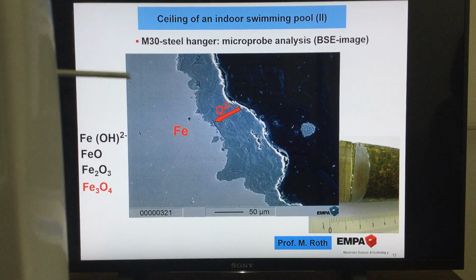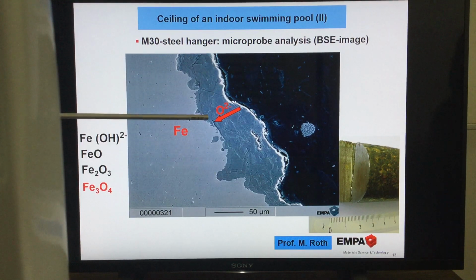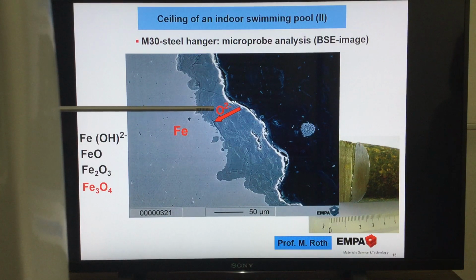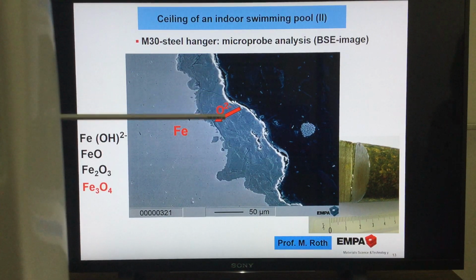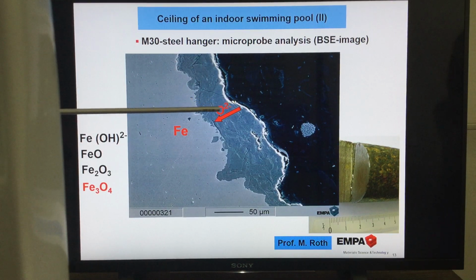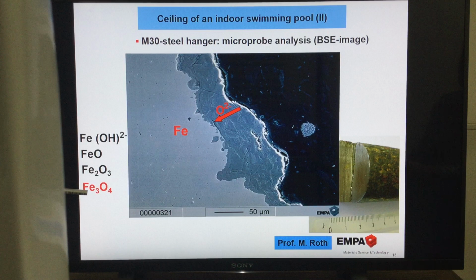The mechanism is that for this front of the oxide layer to move inside, the oxygen, O2-, has to diffuse inside and then can react with iron and grow inward. However, our knowledge about oxidation of iron is the following. These are the different steps of iron oxidation. The first one starts with iron and these OH groups, then the next one, FeO, then Fe2O3, and the last one is Fe3O4.